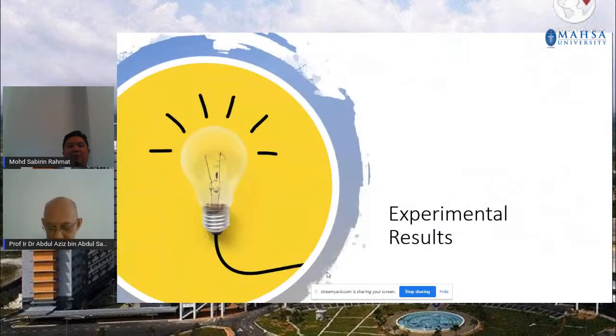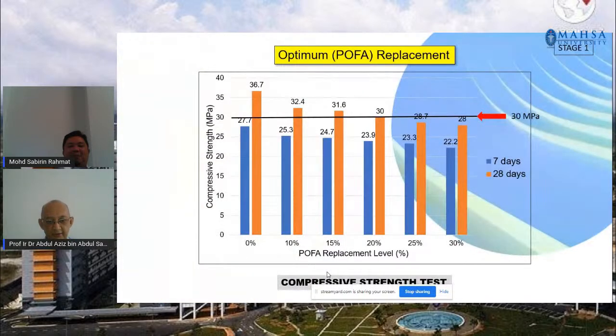So we now can come to the experimental results. What I did now is, this is stage 1. As I mentioned, we have 4 stages: stage 1, 2, 3, and 4. This is the first stage where we replace cement with palm oil fuel ash, a partial replacement between 10% up to 30% of cement with palm oil fuel ash. And of course, at 0%, that means this is totally using cement with no POFA.